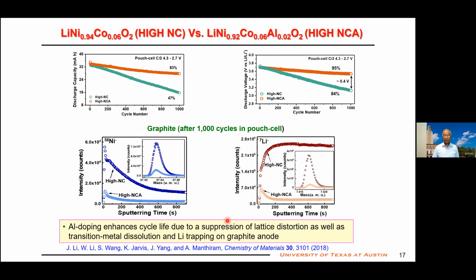Okay, that's all the problem. We understand what we can do to overcome the problematic material. You put 2% aluminum in it. Then you see the cyclability and the voltage stability. You can see the 2% aluminum makes a big difference. The red curve is with aluminum, green is without aluminum. You can see big improvement in the cycle life.